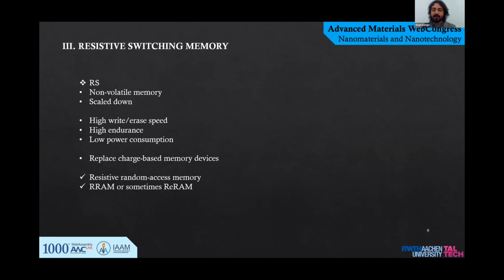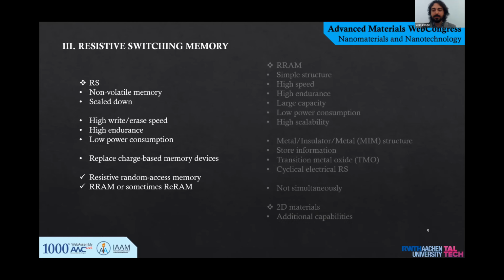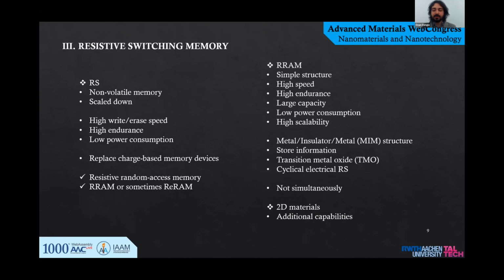Therefore, materials exhibiting RS behaviors, such as metal oxides, organic polymers, and 2D nanomaterials were examined. Among the alternatives, mainly resistive random access memory, RRAM, seems to be the most promising one. RRAM is a simple structure with high speed, high endurance, large capacity, low power consumption, and high scalability. Currently, RRAMs use a metal-insulator-metal structure to store information, where the insulator, usually a transition metal oxide, allows cyclical electrical RS. However, any single RRAM is not capable of showing all these high performance qualities simultaneously. To solve this issue, the metallic or insulating films can be replaced by some 2D materials and provide additional capabilities to the devices like flexibility and transparency.